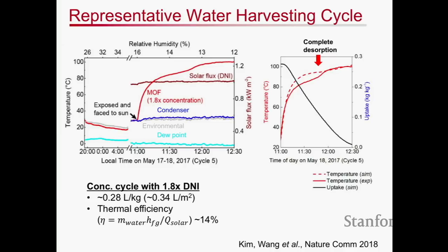What this suggests is that we've been able to get about 0.3 liters per kilogram of this metal organic framework. And certainly there's still a lot of opportunity space, in further tailoring these materials, which are potentially still not optimal depending on the conditions, and also in how to scale up this device so that it can deliver, say, on the order of a family size unit, say 15 liters or so. We anticipate a design of about 30 liters, maybe a suitcase size type system, to deliver that 15 liters of water for a family.